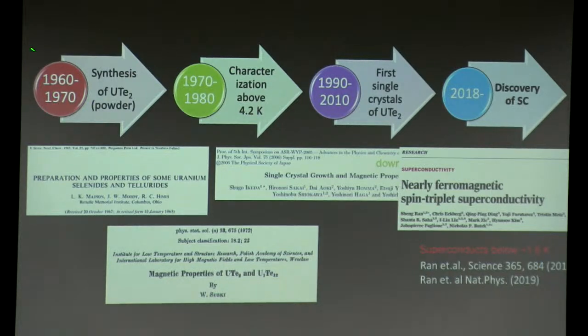Uranium ditelluride has been known for a very long time, more than 50 years. It was first synthesized as a powder, and as soon as it was made into a single crystal in the early 2000s, it was known to be a heavy fermion compound. There's a huge gap between the 2000s and 2018, when superconductivity was discovered, and I think one reason is that the superconducting phase in uranium ditelluride is very sensitive to the uranium-tellurium ratio, so for a long time perfectly stoichiometric compounds turned out not to be superconducting.